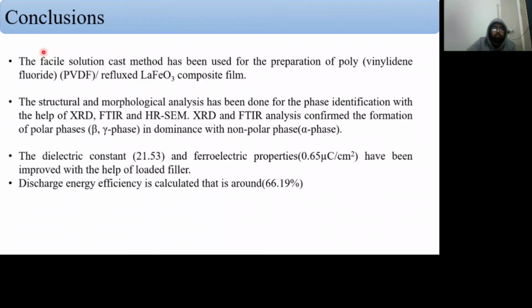Conclusions. The conclusions are that we have synthesized the PVDF refluxed lanthanum iron oxide nanocomposite film with the help of the solution cast method, and we have detected the beta and gamma polar phases with the help of XRD and FTIR, and then we got the enhanced dielectric constant and ferroelectric property by using this lanthanum iron oxide filler, and we have got the discharge energy efficiency around 66.19%.